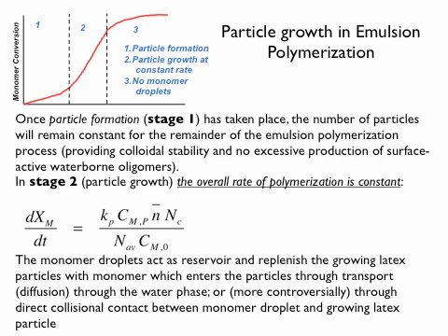So this is a typical equation that holds for emulsion polymerization. There are a few things that you want to know. kp, the rate coefficient of propagation, is known. It's measured by people doing pulsed laser polymerization, and you can look up the values under a variety of conditions and temperatures.